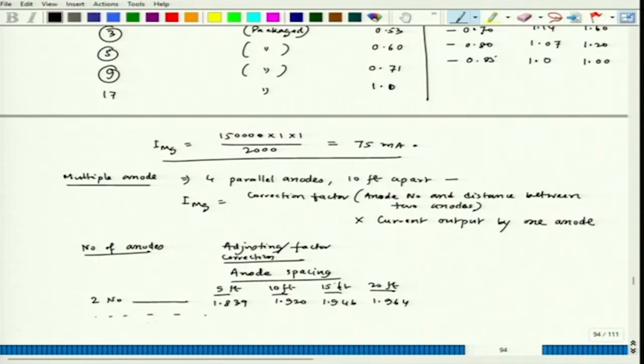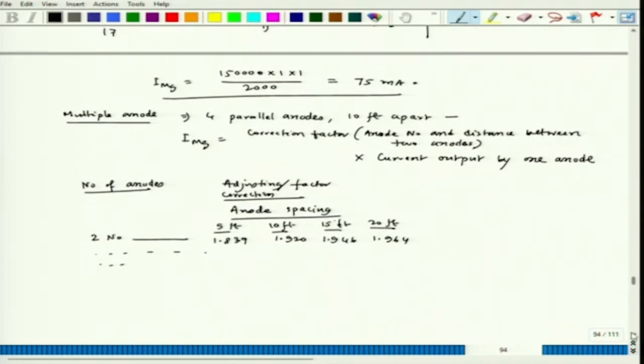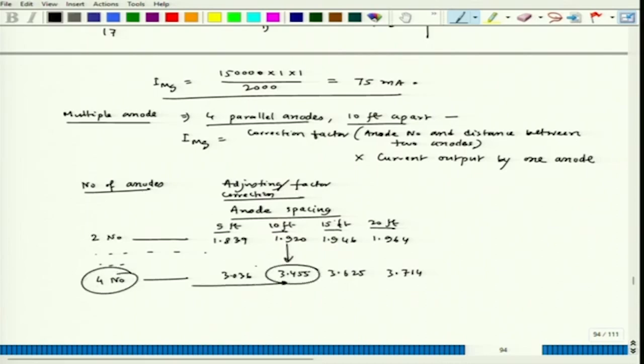Like that you can find values for different numbers of anodes. Now, we are considering 4 anodes. These values for different anode spacing become like this: when it is 5 feet away, 10 feet away, and so on, with values such as 3.036, 3.455, 3.714. Now we have put 4 parallel anodes 10 feet apart, so we have to use this 4-anode row of the table. So, this is the value we have to use.